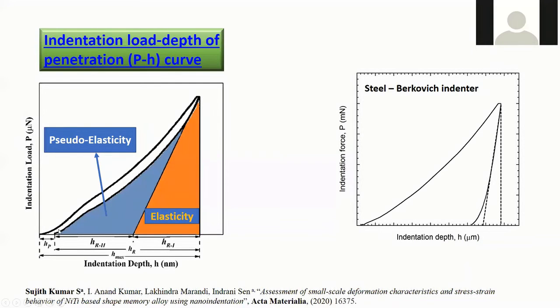Just for you to understand the recoverable strain here, for the case of steel, this blue part is only very, very little. Whereas in the case of nickel titanium, combining both the elasticity and the pseudoelastic part, you can see that quite a large extent of the total depth can be recovered.